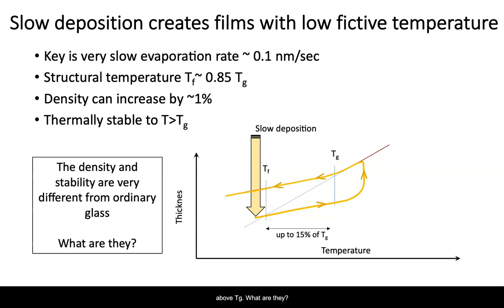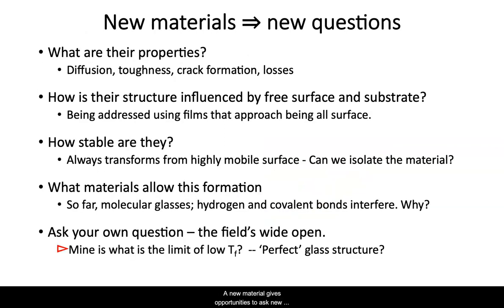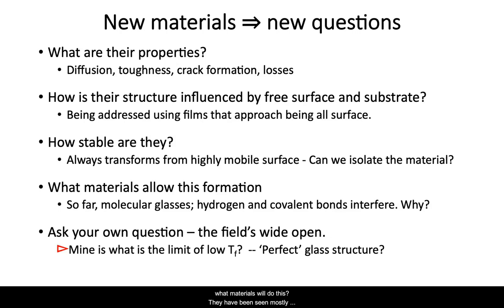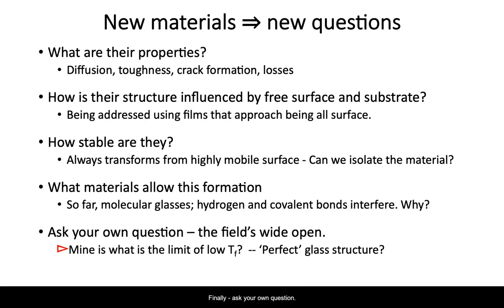So, what are they? New material gives new opportunities to ask questions. First, what are the properties of these films? Diffusion, toughness, crack formation, acoustic loss — all these topics are being addressed in the group. Second, these films have dramatically different properties at their surfaces; we approach that by using very thin films that are nearly all surface. Third, how stable are they? That's been hard to tell because transformation propagates from the free surface. Fourth, what materials will do this? They've been seen in molecular solids bound by van der Waals forces; the presence of hydrogen and covalent bonds interferes. We're examining that using selenium, which forms covalent chains. Finally, my question is: what is the limit of the low fictive temperature?